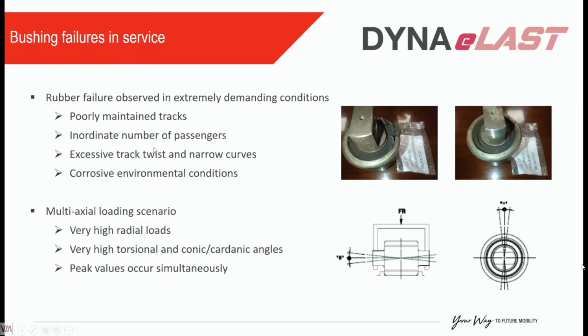There are projects in which the track is very, very stringent for the suspension. So we have track twists that are very high, and we have very narrow curves. And also they tend to be corrosive environmental conditions, particularly in coastal areas. So it doesn't happen often, but when it happens, it is because of a combination of all this. To be honest, we can't really design for this, but the poor maintenance of the tracks is usually beyond what we can do. So we need to deal with it when we have the problem.